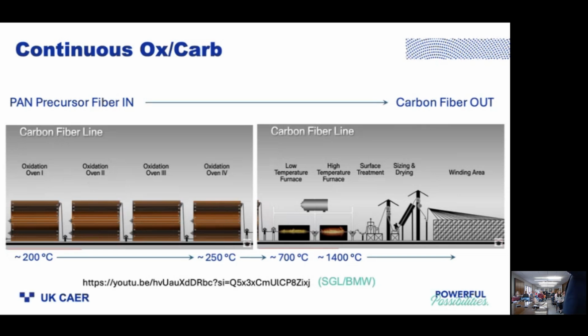However, on the carbonization side, we have what we call our low temp and high temp carbonizations. Those processes happen on the order of about 100 seconds. So the oxidation side of producing pan-based carbon fiber is slow, really slow.